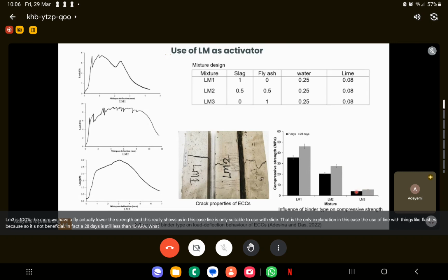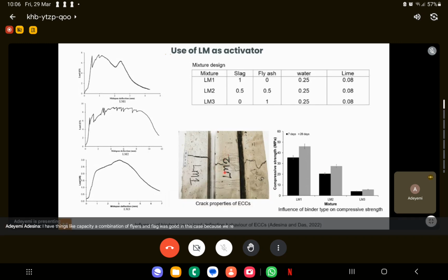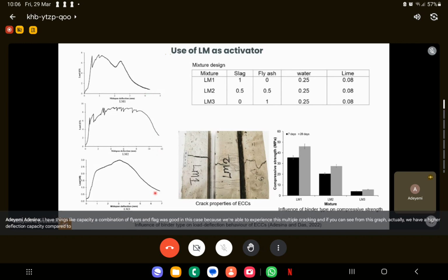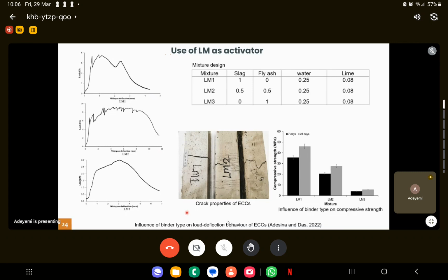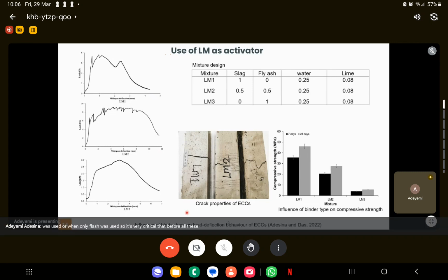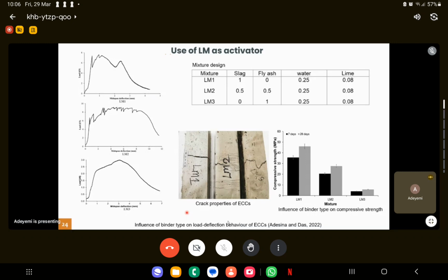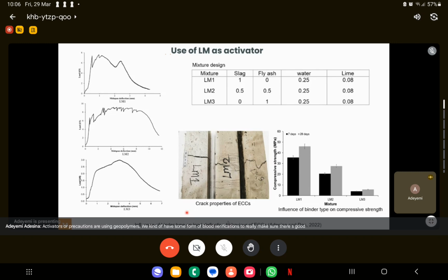But in cases where you're looking for this multiple cracking, higher tensile capacity, a combination of fly ash and slag was good in this case because we're able to experience this multiple cracking. And if you can see from this graph, we have a higher deflection capacity compared to when only slag was used or when only fly ash was used. So it's very critical that before all these alternative activators or precursors are used in geopolymers, we have some form of lab verifications to really make sure there's good compatibility between the activator and the precursor.